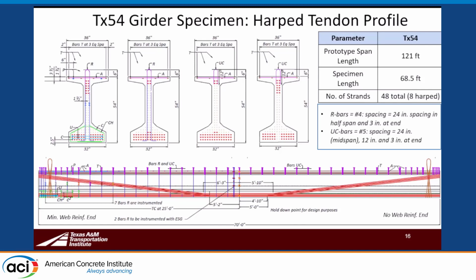We do have some harping. It's just 8 strands out of 48 total. The specimen span, bearing center line to bearing center line, is 68.5 feet. But the loadings that we're mimicking are based on a full-scale design of about 120-foot span. And one thing that I want to point out is that on one half of the span, we do have some web reinforcement, which are called R-bars in the Texas standards. Those R-bars usually will come up and become part of the composite interface shear steel.